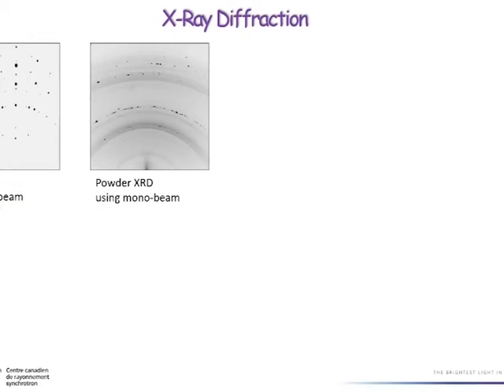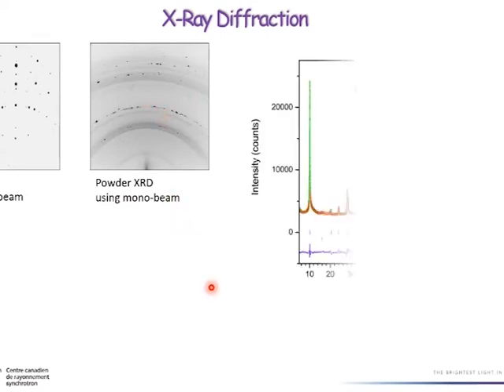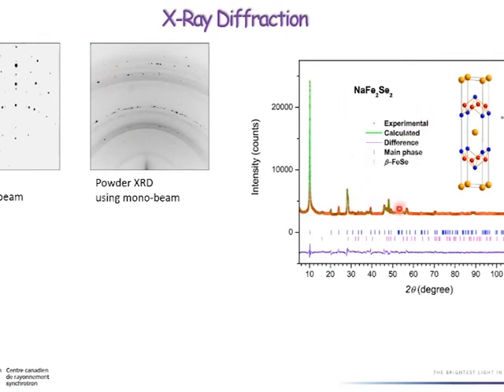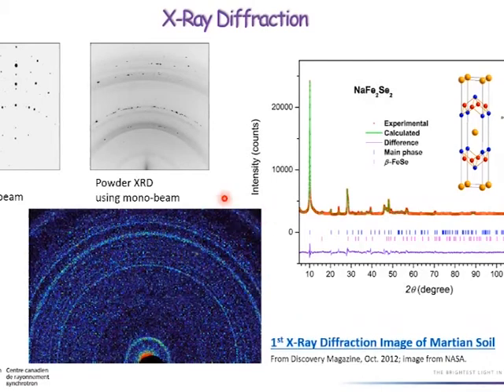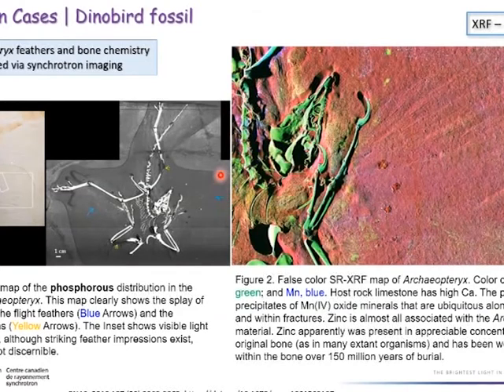The third technique is X-ray diffraction. Depending on the beam type used — polychromatic or monochromatic — you can do Laue diffraction or powder diffraction. The results appear as 2D diffraction rings, which are typically integrated to give a 1D plot of intensity versus 2-theta or d-spacing. Comparing to a database allows us to identify the crystal structure — this is also a fingerprinting technique. The image shown here is a diffraction pattern from Mars soil, giving a real-world impression of what diffraction patterns look like.